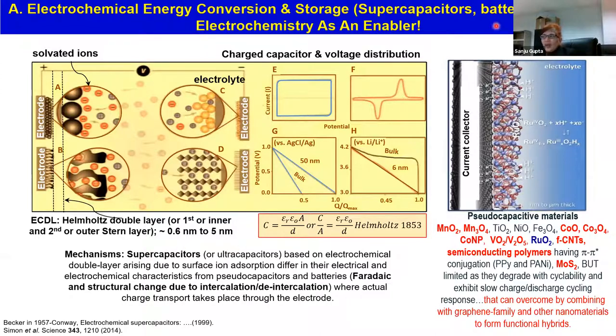As for the battery, the mechanism by which the supercapacitor stores charge is through surface ion adsorption. Unlike in pseudocapacitors, where actual electron transfer takes place between the electrode and the electrolyte. And on top of that, if there's a structural change because of the insertion of lithium ions, as in the lithium ion batteries we all use in our laptops, for instance, an actual structural change takes place. So these are three mechanisms that can at times all play together.